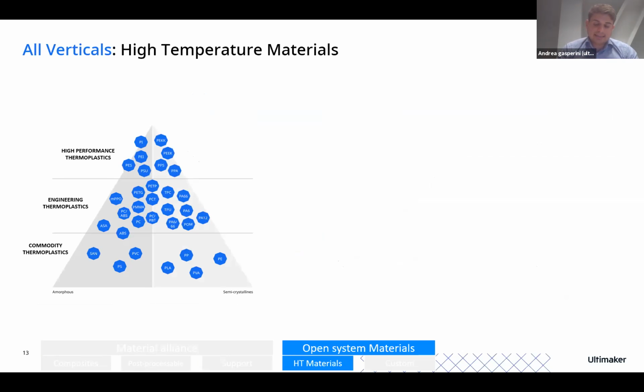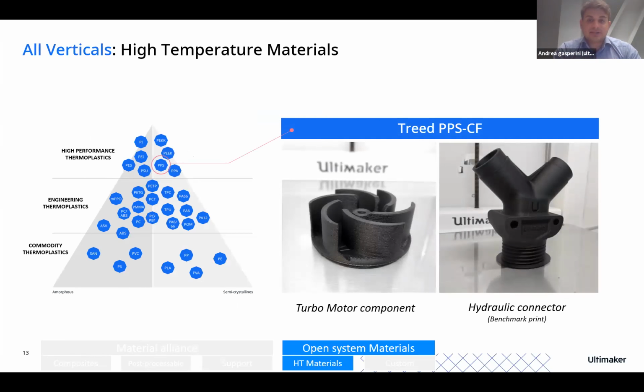Then I'm going to switch to the section of open material system, and here I'm showing you something really outside of the specification of Ultimaker for now. So it means it's a material that can definitely be used on an Ultimaker, but is outside of the specifics. And this is the PPS carbon fiber. It prints extremely well. It's part of the family of high temperature thermoplastics. We're talking about a material that has a peak temperature resistance of 240 degrees for a really short time, and a pretty good and constant stability around 210, 220 degrees on stable working operation.